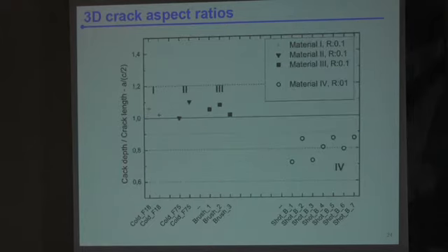So if you study this value, which is the steady state crack aspect ratio for different samples of the same material, you see more clearly the trend. Materials 1, 2, and 3 are above 1, while clearly for material number 4, for those 7 samples, you are clearly below. So there is a change in the crack aspect ratio for this material. And this was, I think, where we were at that stage when we went to Urbino.